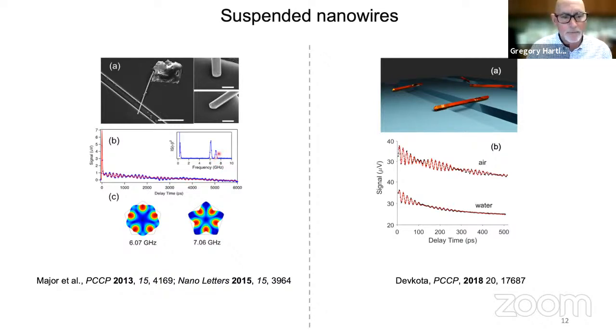Okay. In general, we like to look at much smaller structures. With smaller structures, we can't see them by SEM, so we don't know their dimensions, we just measure their frequencies. And so these are some examples over on the right here of traces for some smaller structures, much higher frequencies. These are again nanowires. You see these two frequencies going in and out of phase, one in air, and then in this experiment, we put this structure in water, and you can see that the modes are damped by the interaction with the liquid.